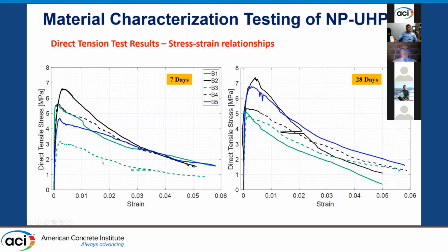So these are just some of the results here. Again, what did we want to show here? The 1% and 2% obviously will have different results. We wanted to show the general trend. If we just focus on the very first part, you will see some strain hardening, but we are plotting it all the way up to 5% strain to show that the ductility is there. The idea here is to provide sample full stress-strain curves for this material using different batches, for those who would like to pick these later on for modeling purposes or analytical assessment.